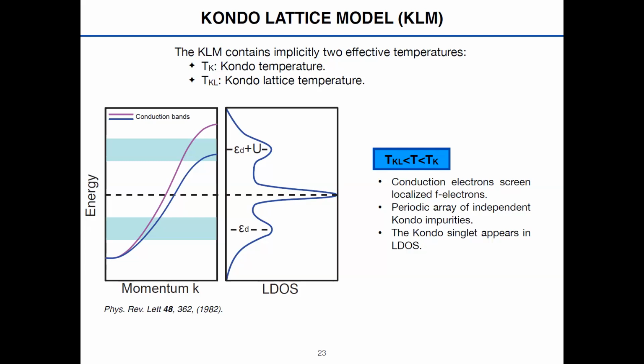so the 1T layer and the 2H are decoupled. Okay, there's some interaction because the conduction electrons of the 2H are screening the moments of the localized electron, and therefore when you do this spectroscopy, you see the zero bias resonance. Okay, but you have this periodic array of independent Kondo impurities.